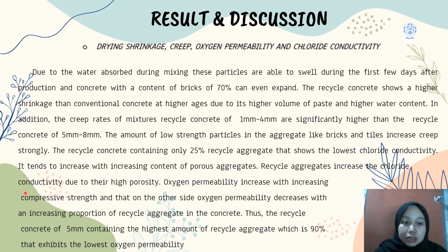The recycled concrete containing only 25% recycled aggregate shows the lowest chloride conductivity. It means that only 25% of recycled aggregate has proven the lowest chloride conductivity, and it tends to increase with increasing content of porous aggregate. Recycled aggregate increases the chloride conductivity due to its high porosity.